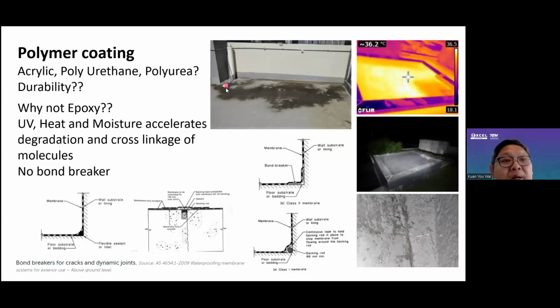Okay. And polymer coating like acrylic, polyurethane, and polyurea. How durable it is, I do not have information about polyurea, but so far as my inspection is concerned, I discovered polymer coating is also not suitable, especially if there is presence of ponding water. It typically will wrinkle and it will start to break down at a location with ponding water. And secondly, likewise to other coating, we can also check the failure of coating using infrared imaging.